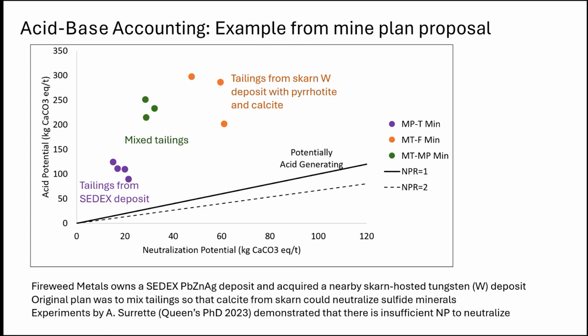So the background here is a company called Fireweed Metals. It owns a SEDEX deposit. I expect you've heard about those, the lead zinc silver deposit. It recently acquired a nearby skarn-hosted tungsten deposit. And Fireweed proposed in one of their early plans to mix the tailings, with the idea that, hey, it's a skarn, it has lots of calcite, and that could neutralize the sulfide minerals, because the SEDEX deposit was sulfidic, and actually the carbonate it had was mostly siderite. I was able to tell them that with a little testing.